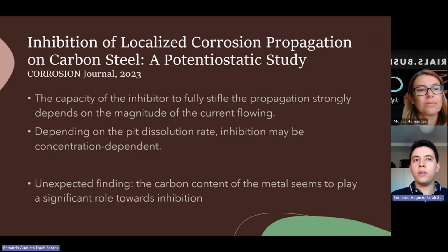But what happens is that when the material is corroding at the corrosion potential, that's just the OCP, what we call, right? But when you're polarizing the surface, you're artificially increasing the dissolution rate of that sample, right? So that value for surface saturation concentration of the inhibitor is no longer reliable, let's put it like that. So depending on the condition that you are in doing this kind of experiment, you may need to increase the concentration of the inhibitor. So those were, let's say, the main findings.